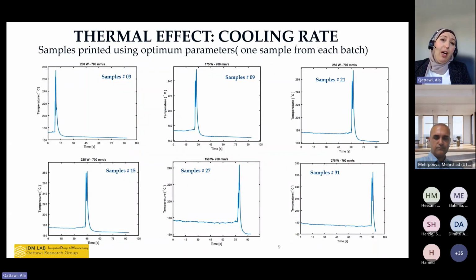To give you an insight of how this looks, we collected many images through the print. Each sample can have millions of images across the whole print, because we take one image every 30 seconds, or if I'm correct, 20 seconds. And all these layers need to be on top of each other to get the whole part. But to give you a glimpse of what this data looks like, if you look at the thermal effect for cooling rate, you can see that each of these samples has a different laser power and different laser speeds within the same alloying system, the iron shape memory, but results in a different cooling rate.